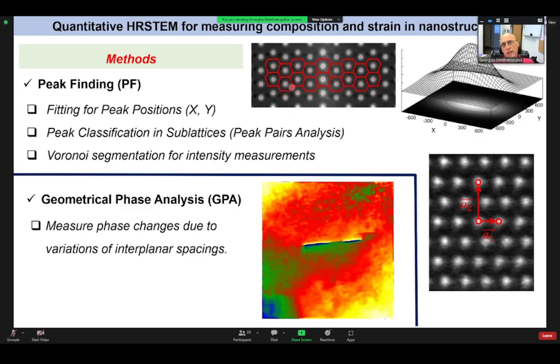Also, in order to be able to do such quantification, you need to be able to ask the computer to make a classification of the peaks into sublattices, because maybe your material is not a single lattice, like a simple, let us say, FCC structure. It may be a more complicated structure like this, which is hexagonal. And in hexagonal close-packed structure, we have two interpenetrating sublattices, the A sublattice and the B sublattice. So the computer must be able to know the sublattices. So it must be able to define the nearest neighbor positions for each atomic column.